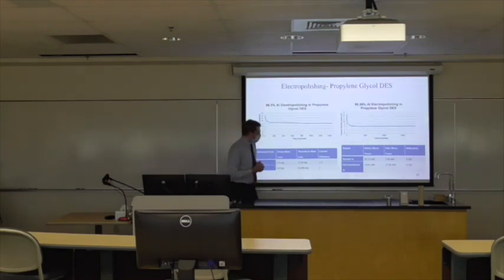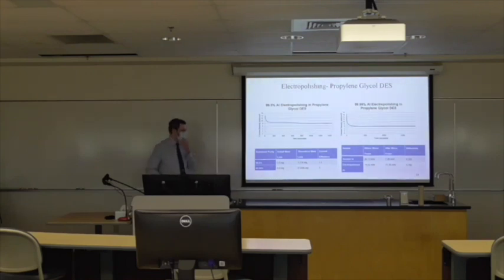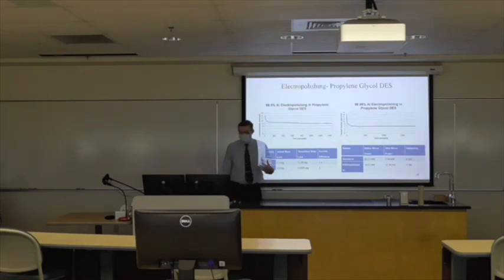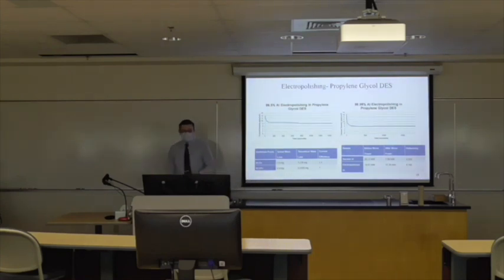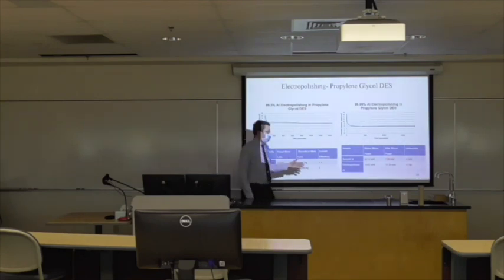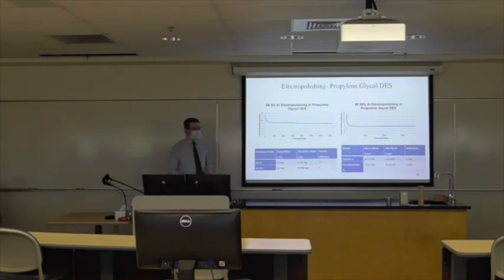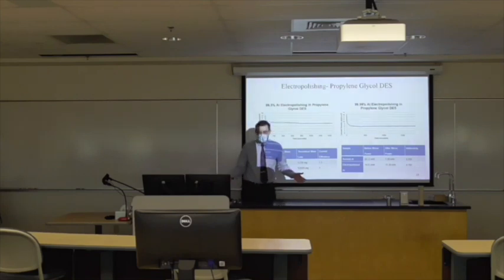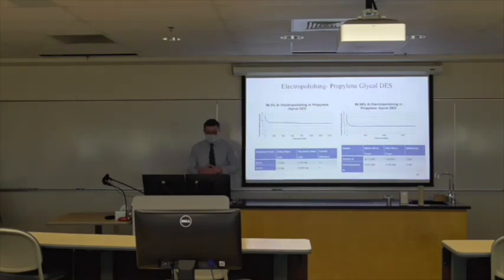For a better way of describing how well the polishing actually worked, one thing that we had done was use a laser to try and figure out the reflectivity. And how we are describing that reflectivity is: the greater the reflectivity, the less scattering that you would see of the light from the laser when it is shining on a piece of aluminum.